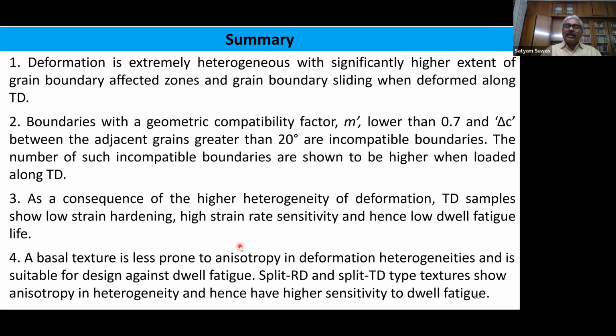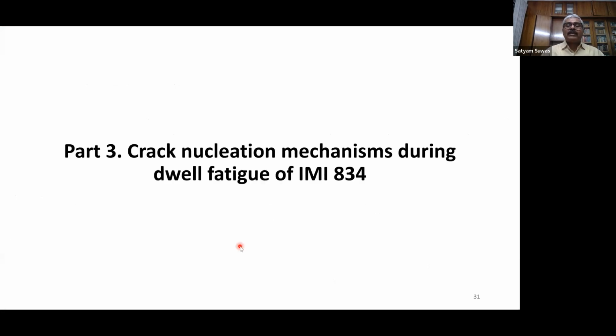And the split RD and split TD type textures show anisotropy in heterogeneity, hence have higher sensitivity to dwell fatigue. So this was also a conclusion. Now, what are the crack nucleation mechanisms? So far, we have seen in what conditions cracks are forming, under what situations of grain boundaries, what conditions of Schmid factor, what conditions of orientation. We are getting a situation that leads to crack formation.